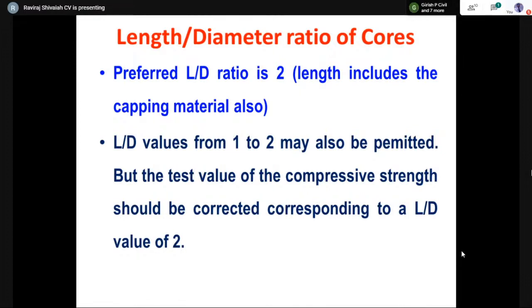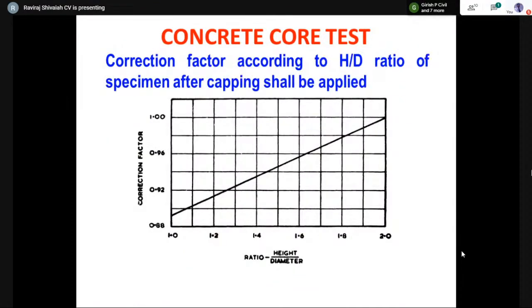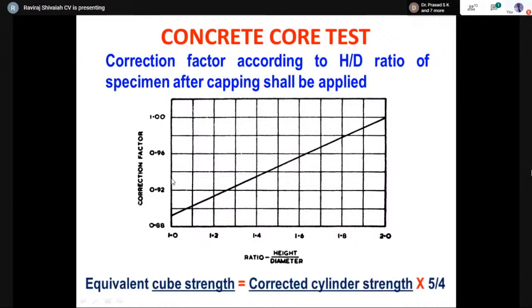It could be less than 2, in which case we do a very simple correction factor using these kinds of graphs. For example, I have 1.4 as the length to diameter ratio. So I can use this particular table and get a correction factor here. This I can multiply on the value that I get from the compressive strength on that particular core that I have tested. And whatever cylinder value I get, I can multiply by 1.25 to get an approximate equivalent cube strength.